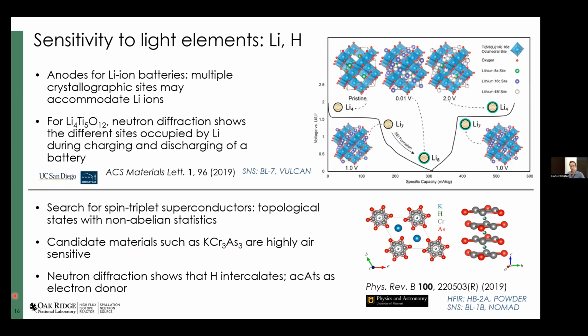neutron diffraction, you can also determine where hydrogen is. And there was not an intent to have hydrogen in these samples, but in the process, there was some chemical processing and some washing that actually resulted in introduction of hydrogen that wasn't seen by any other technique. And it turns out that the hydrogen actually really affects the electronic properties of the superconductor.